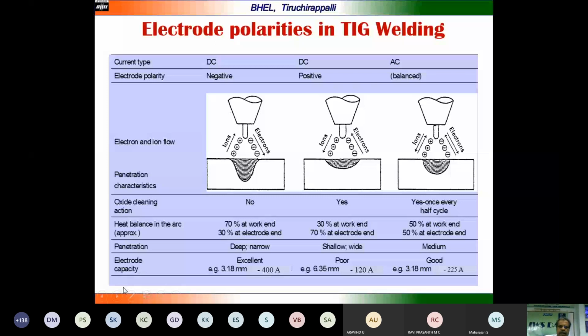If you take DC electrode negative, the positive ions are moving towards the electrode, and the electrons are coming towards the job, and there is no cleaning action. 70% of the heat is available in the work part, and 30% at the electrode end, and that's why we are able to get a deep penetration and a narrow bead width. It has excellent electrode capacity, because even with a 3.18 mm diameter, 180 mm long electrode, you can go up to 400 amps current, because only 30% of the heat is available in the tungsten electrode.